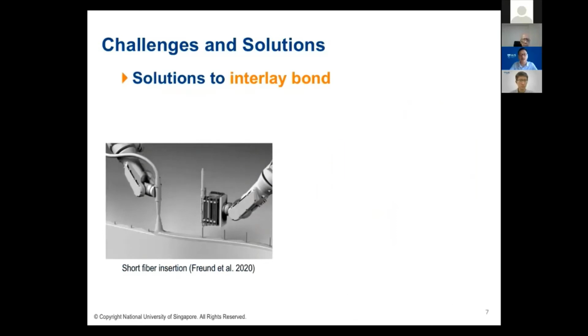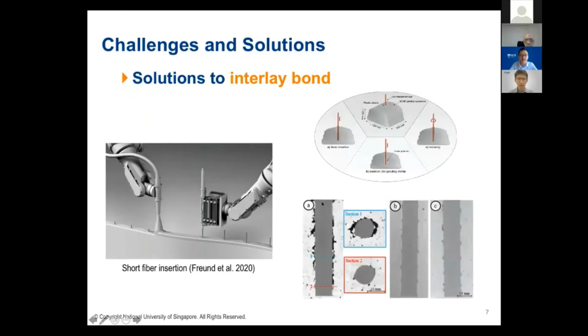There are a few ways, 2 main categories: mechanically and chemically. So one researcher from Germany is using a robot to print concrete, and at the same time, he used a robot to insert a steel rebar. But the steel rebar is not continuous, it's just a short rebar to improve the interlayer performance. And the researchers investigated the way they insert the short rebars, including direct insertion or screwing, or a combination with insertion with grouting. So he has investigated the interface between the rebar and the matrix.